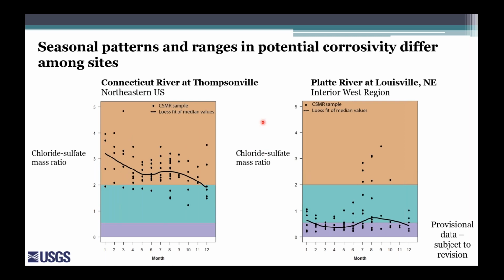Now, if we look at the right-hand side of the slide, we're looking at the Platte River from Louisville, Nebraska, which is in a much different kind of situation than the Connecticut River at Thompsonville. The first thing we'll notice is that the chloride to sulfate mass ratios overall are much lower in the Platte River at Louisville, Nebraska. And they're, for the most part, not above 2, and many of the observations are actually below the 0.5 limit where the chloride to sulfate mass ratio could promote corrosion at all.